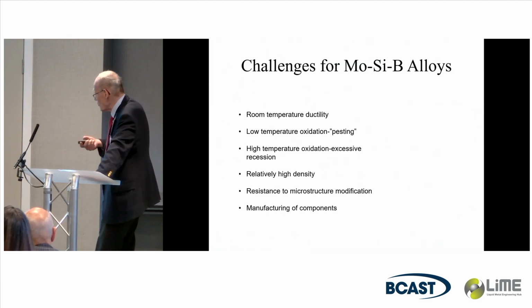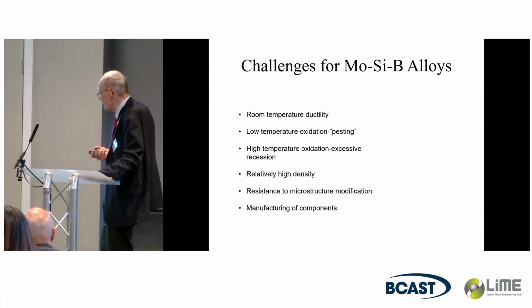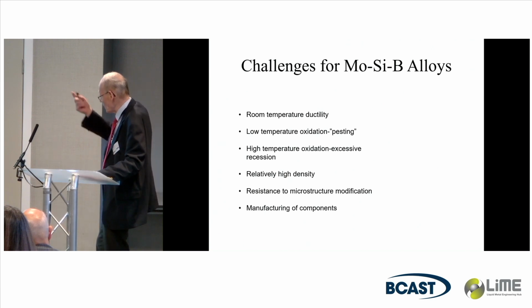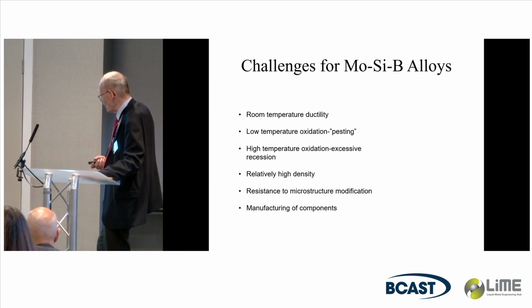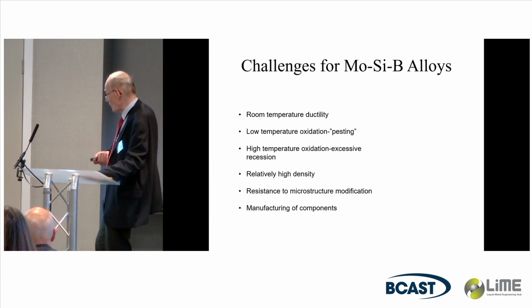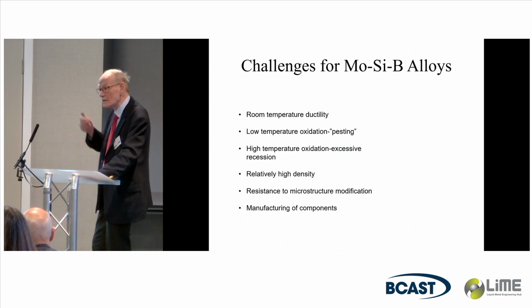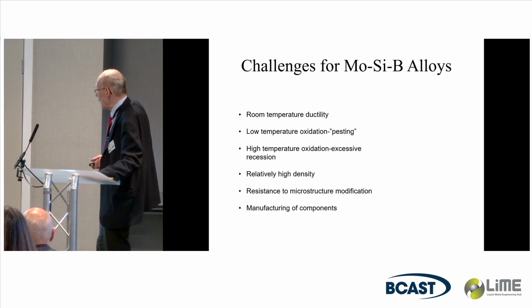All right, so these are the issues we have with room temperature ductility, low temperature oxidation. There's pesting that occurs. You get excessive oxidation until the coating, the borosilica, forms. High temperature oxidation with excessive recession. Relatively high density, molybdenum is over 10, whereas the nickel-based alloys are around 9 grams per cubic centimeter.